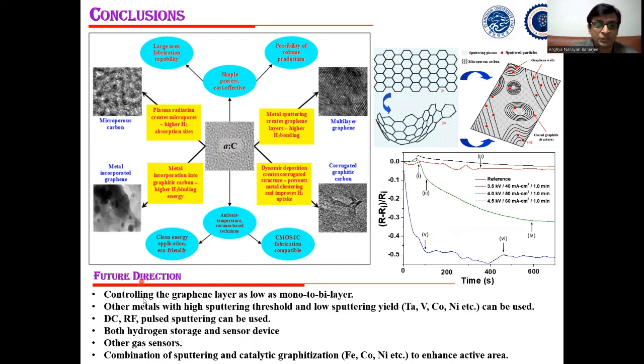In terms of future direction, we want to control the graphene layer up to mono to bilayer, and also use some other metal nanoparticles which have high sputtering threshold and low sputtering yield, to control the sputtering parameters as well as the graphitic network more easily. We can also use DC, RF and pulse sputtering techniques to control the graphitic network more easily. This can also be used as hydrogen storage as well as hydrogen sensor devices, and a similar method can be used for other gas sensor applications.